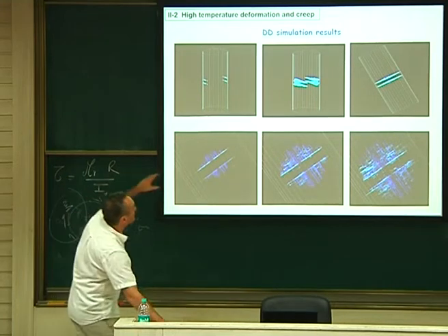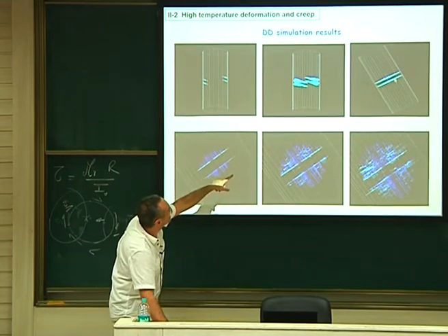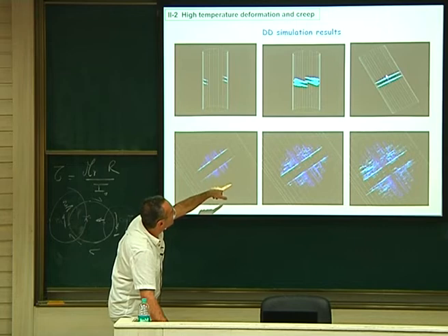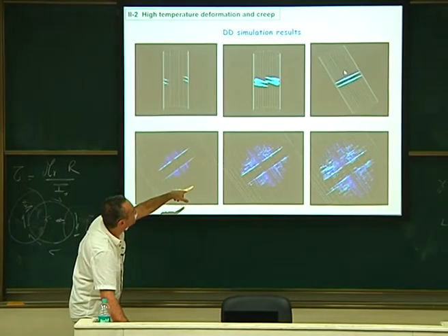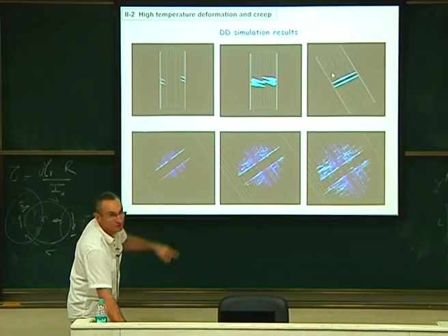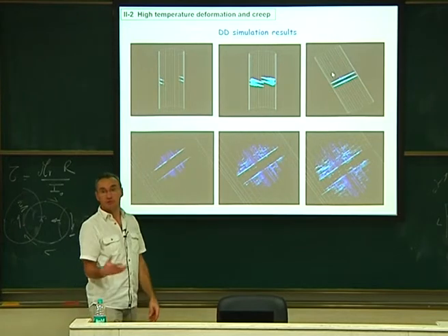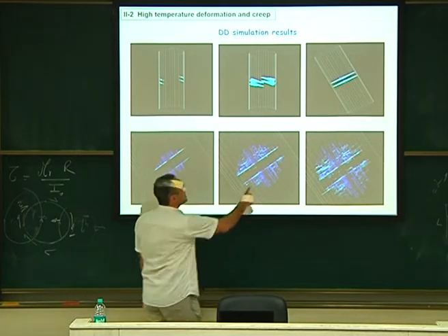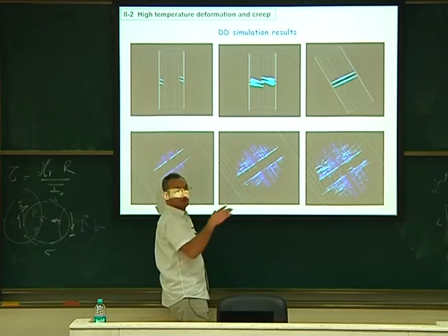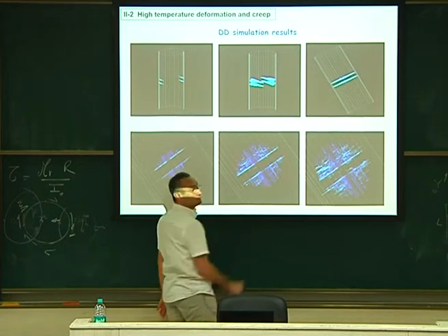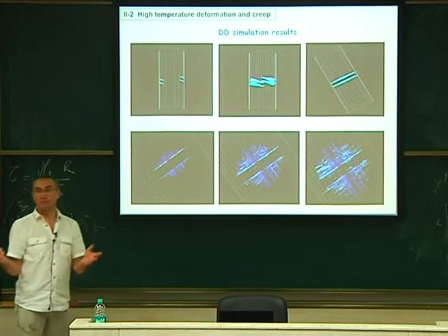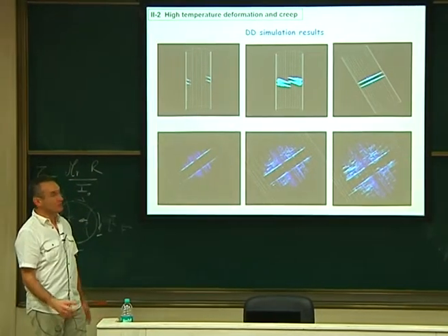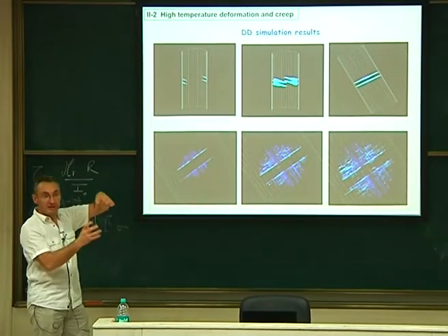If I was doing it here, maybe we can see. It's coming toward the center, cross-slipping, and then you have new planes, and then cross-slipping, new plane, cross-slipping, new plane, and so on. Similarly to what we could have in FCC, except that here the cross-slip is at 90 degrees. There is not a 60 degrees angle, it's a 90 degrees cross-slip. And just with the law we put, it's able to invade and propagate plasticity plane by plane.